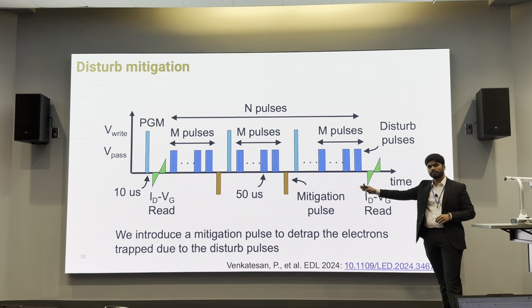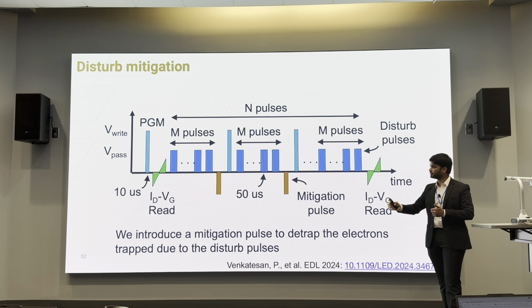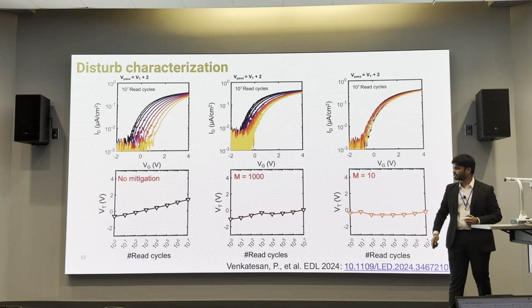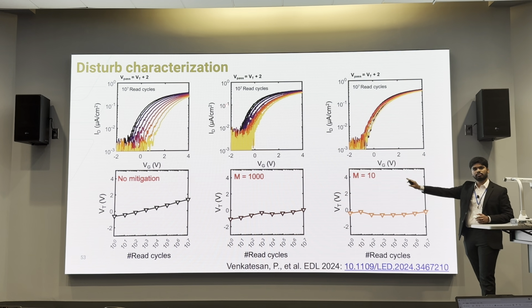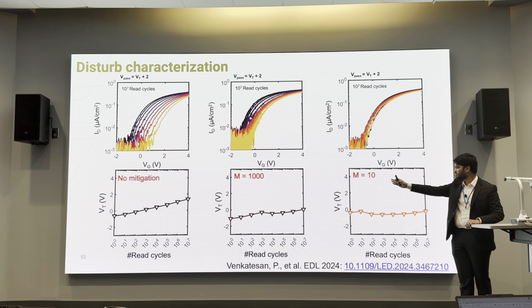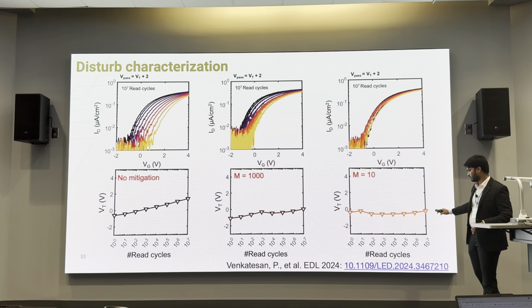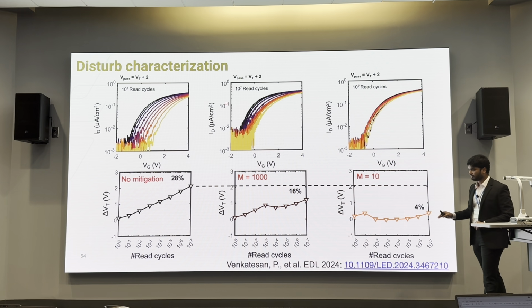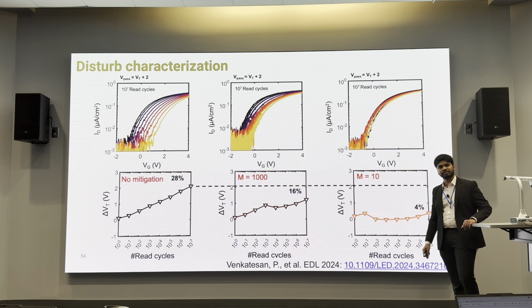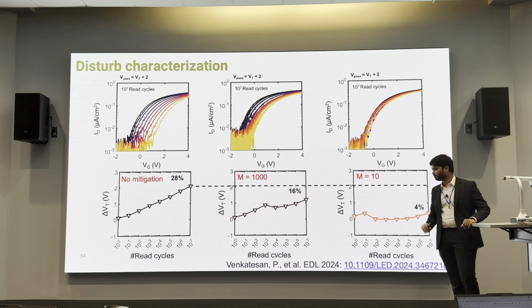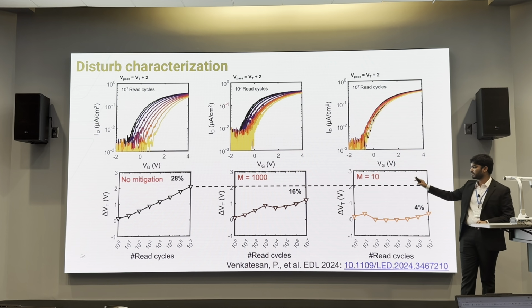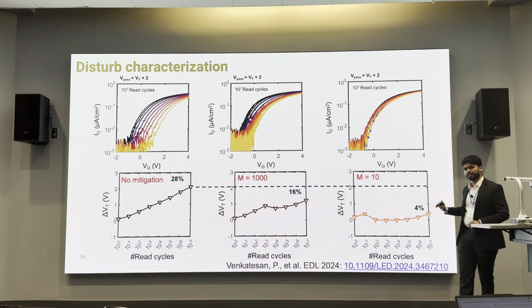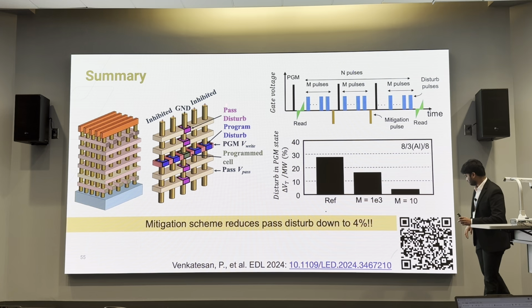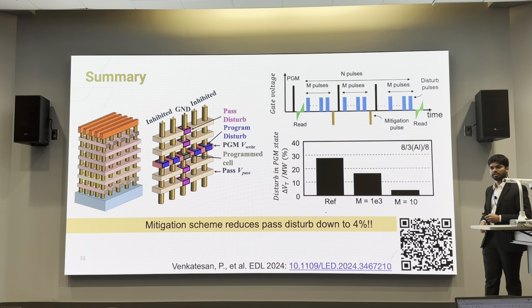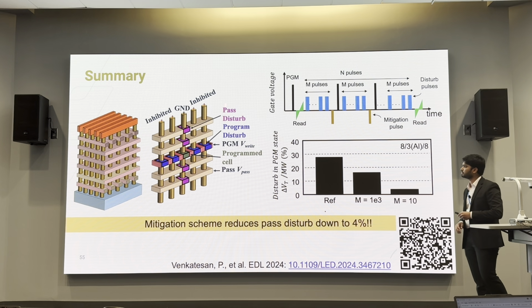So we introduced a disturb mitigation scheme where we apply a negative voltage to detrap these electrons that are trapped during the positive pulses and then refresh the device. So what happened when we did this? We immediately saw results where when we applied a refresh pulse every 1000 access times and every 10 access times, we saw huge improvement in terms of threshold voltage shift. So to quantify it, without any mitigation scheme, we have a 28% degradation in the threshold voltage. With the refresh being applied every 1000 accesses and every 10 accesses, we could reduce it down to 16% and 4% respectively. So in the slides, there are also QR codes for you to access the journal publications corresponding to all the results that are being presented here.